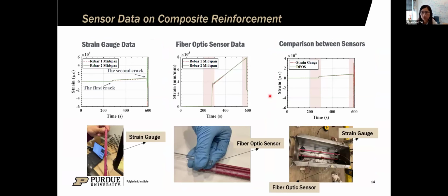So here are the sensor data results collected from the fiber optic sensor and the strain gauge. We compared the strain data of the 2 rebars and the sensor data collected by the different sensors. Since we have 2 symmetric composite rebars in the bottom area of the concrete beam, the sensors on the two rebars should provide the same values, as you can see in the first two figures. And the strain measured by the fiber optic sensors matches quite well with the strain measured by the strain gauge at the same location, as you can see in the third image.